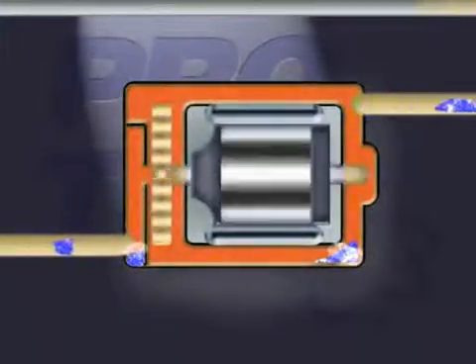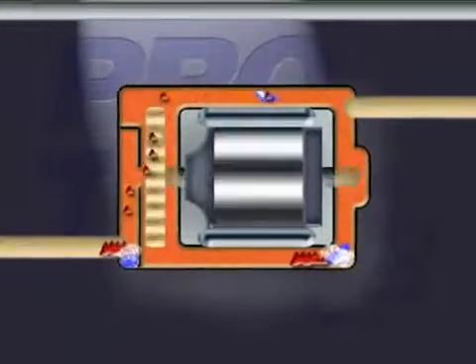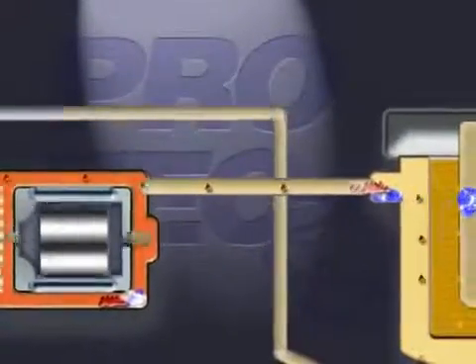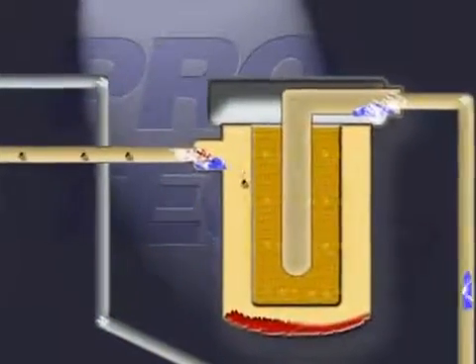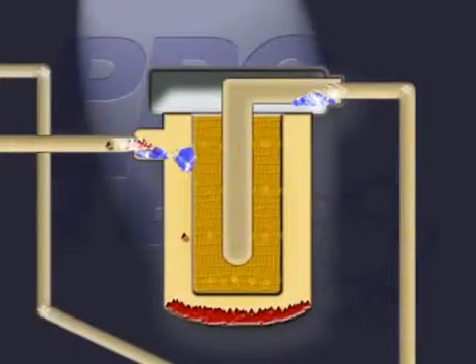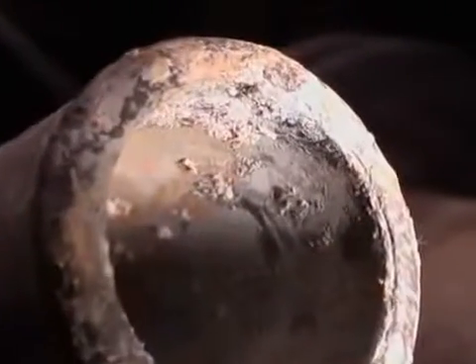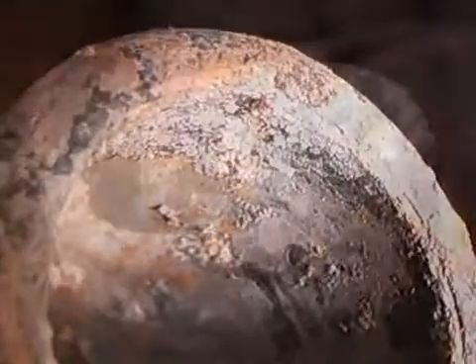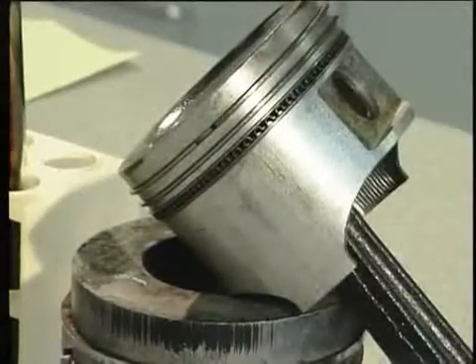The fuel pump then ensures that this is distributed through the rest of the system. This highly aggressive alcohol-water mixture then passes through the fuel filter unhindered and has a destructive effect on all the component materials downstream. Aluminium parts are particularly at risk. Aluminium hydroxide can be formed in them and is well known as a white powder. But cast metal parts, elastomers, fuel pipes and piston heads and rings are just as much at risk.